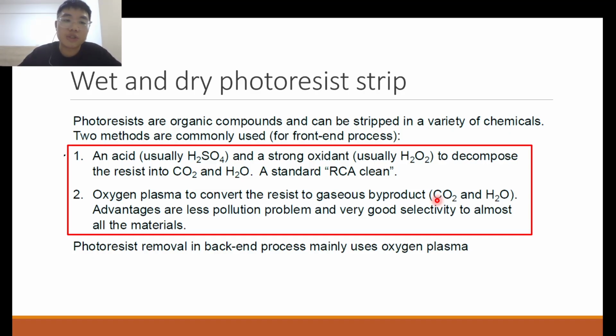There are two ways to strip your photoresist. The first way is to use an acid and a strong oxidant, and this basically oxidizes your organic photoresist, because your photoresist is an organic compound. This combination of oxidizing acidic environment is able to oxidize your photoresist into carbon dioxide and water.